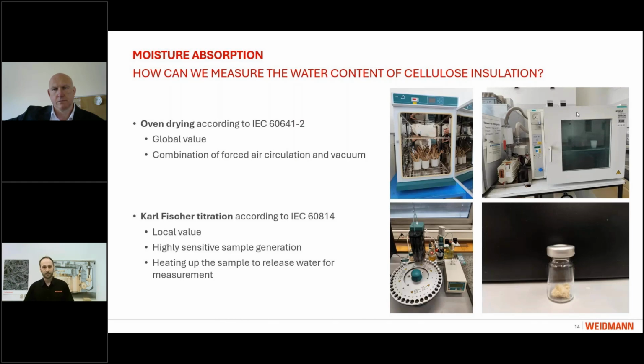What is also quite critical here is that, due to the small amount of sample that you use for this test, it is a method where sample generation has to be done with really keen eyes. Many of you know this, but I state it again: 90% of mismanaged sample readings come from sample preparation. So this is really a test where you need to be very careful in handling, use gloves, don't expose the sample to environmental conditions, but really make sure that in between sampling and measurement, there is only a small time and you have control over the ambient conditions of that sample. Also in that method, of course, in the end, you have to heat the sample to release the water.